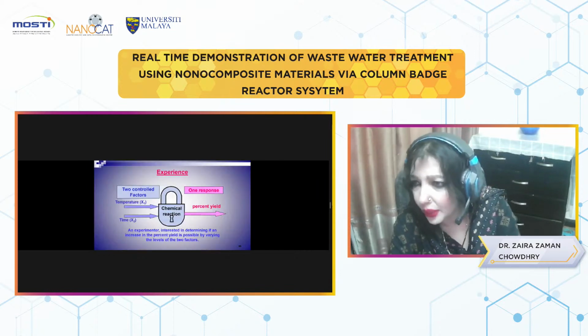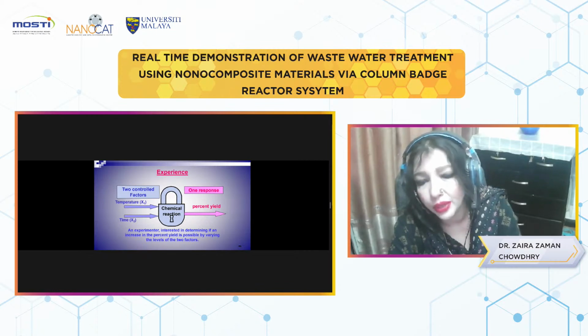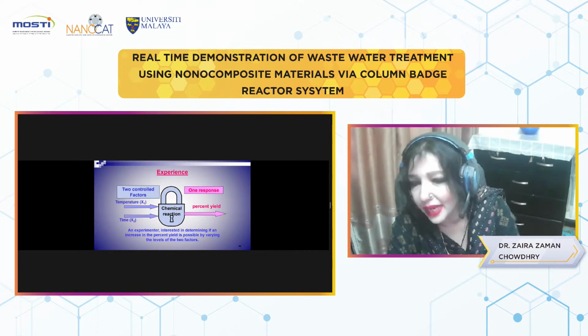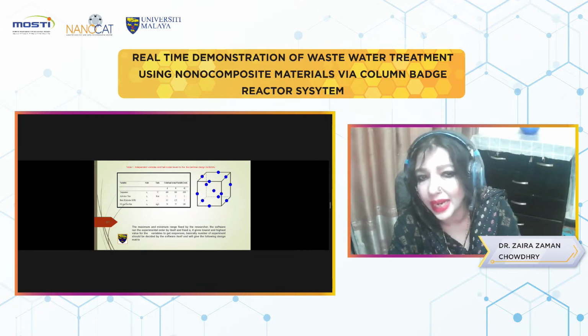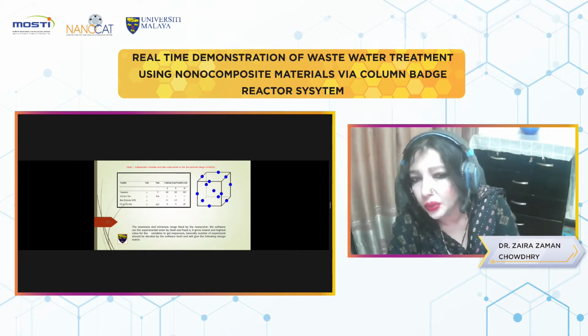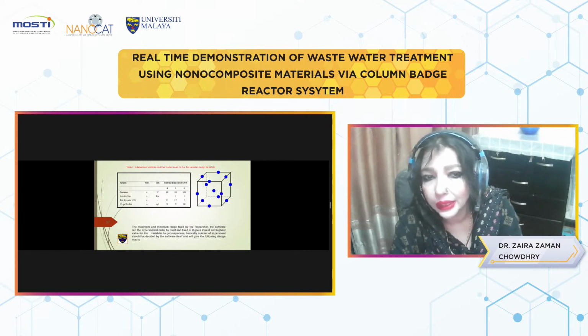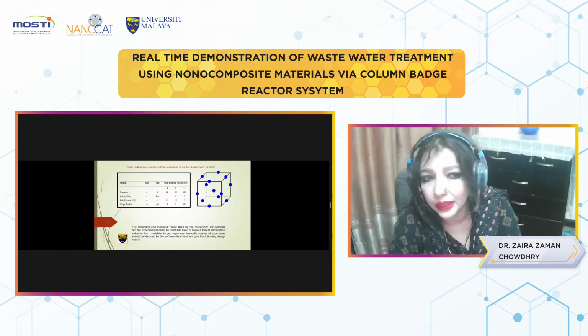I am not going into it elaborately because time is constrained here. We have to finish quickly. We have used BBD design where we have 3 variables: temperature, activation time, and ratio of hydrochar to KOH. So these were our basic variables. We have changed our time from 1 to 3 hours, our ratio of KOH to hydrochar 0.5 to 2, and carbon dioxide gas flow rate 50 to 100.